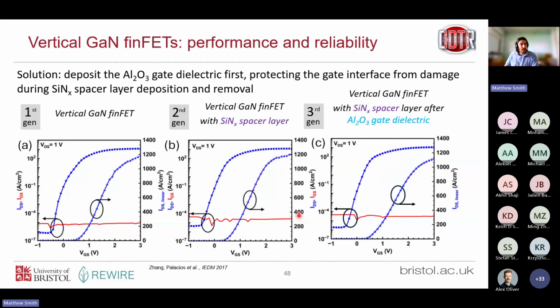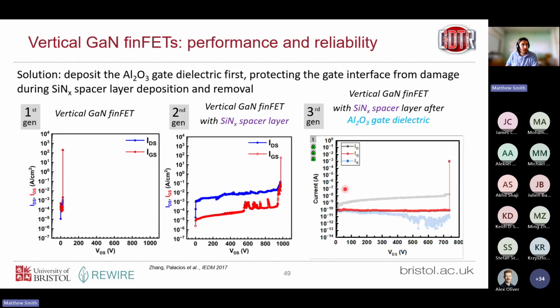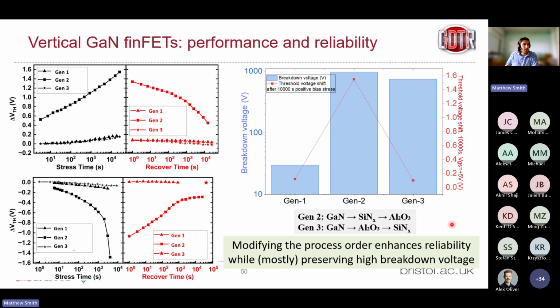So in terms of the on-state performance, third generation devices again look very similar. So again, good news, the modifications to the process that we made didn't affect the on-state performance. But if we look at our off-state performance, so breakdown voltage, there is a slight drop here. So we're at 750 compared to sort of 950, 1000 here. So possibly a slight reduction associated with this process.